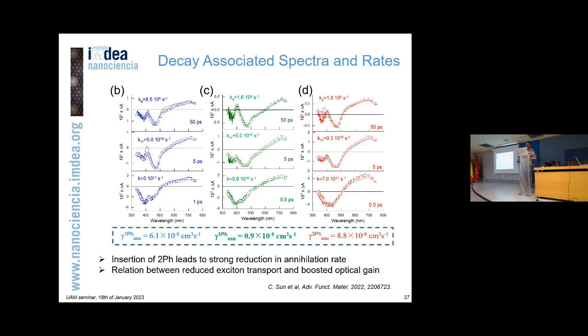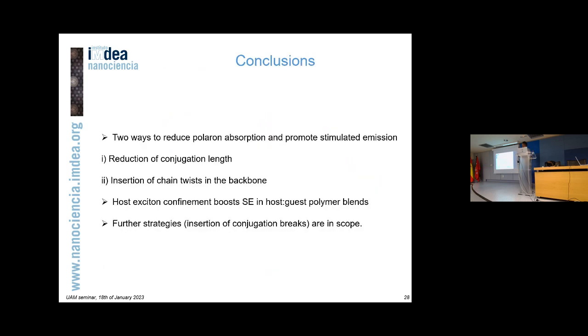So in a way, what we are proposing is that by isolating chains, by reducing this mechanism of annihilation between singlets, we can reduce the probability of polaron formation and effectively obtain stimulated emission. So in a way, this strategy of introducing twist units works, but we don't really have a full answer why it works for 2 units and not for 3, for instance. This is still an open question.